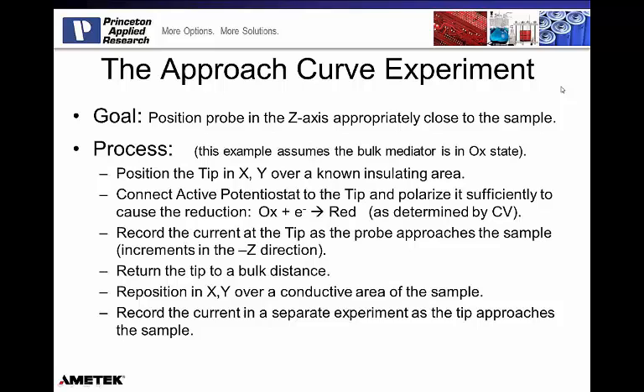Then I'm going to record the current at the tip as the probe approaches the sample in increments of z in the negative z direction. So imagine I've got a probe and it's sufficiently far that I'm getting bulk response away from the sample. Then I'm going to move the probe down in z, and typical values are maybe the radius of the probe. So if I take a 25 micron probe and start making steps down, I want to do that in 10 or even 5 micron steps down. That allows me to acquire the current. Then I'm going to see the response move from the bulk response to the localized response. I'll show you some examples of what that looks like, and some rules of thumb or practical advice on when we can stop these.